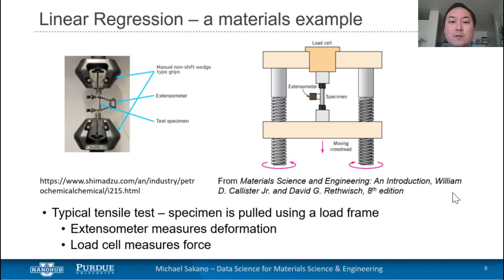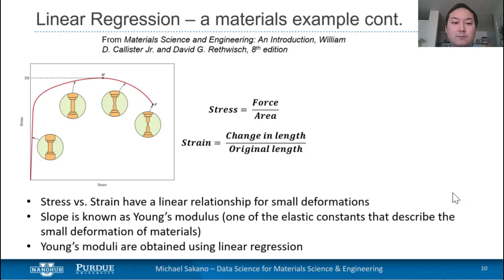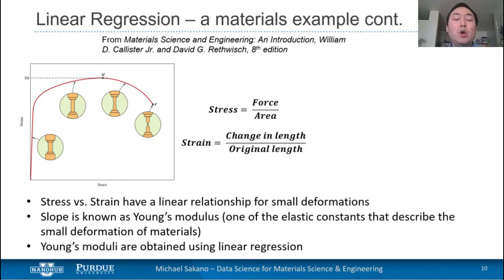The second property is the measure of force via the load cell. If we know the force measured through the load cell and we know the cross-sectional area of our sample, we can measure the stress in units of pressure. If we know information about the deformation — related to the change in length — and we know the original length of our sample, then we can measure the strain, which is unitless. Shown on the left is an example of a stress-strain profile for a material; for very small deformations, we see that stress and strain have a linear relationship, and the slope of this stress-strain curve is known as the Young's modulus, which is just one of a few elastic constants to describe small deformations in these materials.